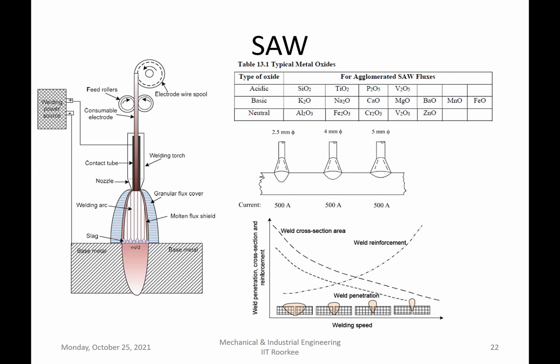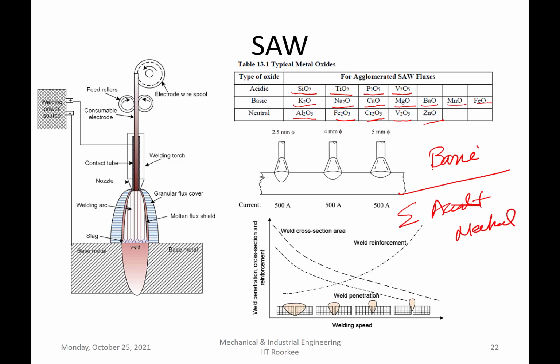Oxide fluxes are of three types: acidic fluxes, basic fluxes, and neutral fluxes. Acidic fluxes are like SiO2, TiO2, then P2O5 and V2O5. Basic fluxes are like potassium oxide, sodium oxide, calcium oxide, magnesium oxide, barium oxide, manganese oxide, iron oxide. Neutral fluxes are like Al2O3, Fe2O3, Cr2O3, V2O3 and ZnO. So basically, whatever is the weight percentage of the basic fluxes divided by all non-basic fluxes, meaning the sum of the acidic plus the neutral fluxes, whatever you have in a flux, that dictates the basicity index.